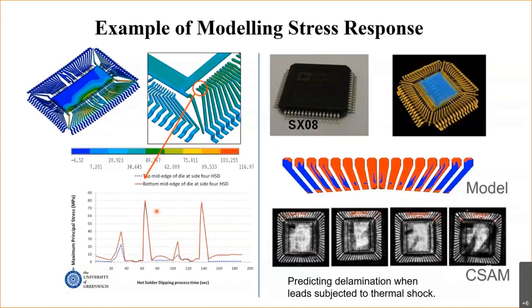We were raised the question, if we expose the package to extreme temperature loads, a big thermal shock, you're predicting stresses, but could you predict delamination? And here we see the model prediction when the side of the package has been exposed to a very severe temperature load. So these are showing where it's red that delamination would occur. And for that particular package, we could see here from the CSAM data where the delamination has occurred.